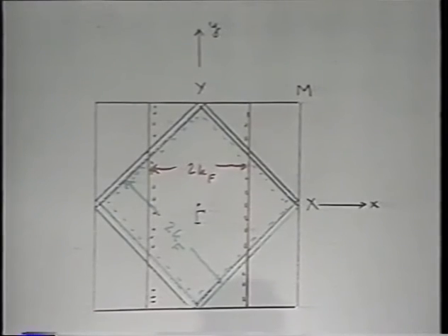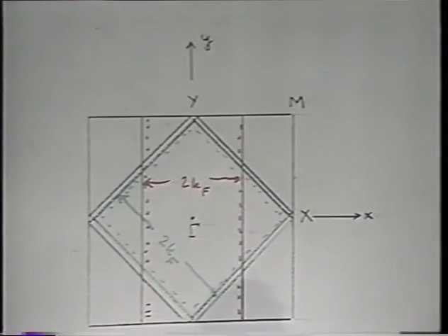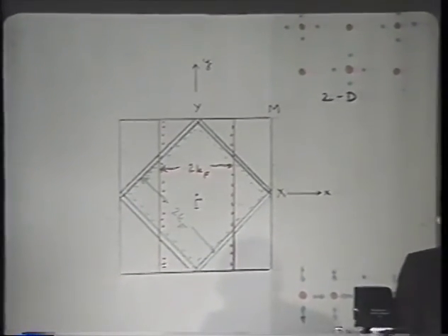They, too, give rise to sheet-like Fermi surfaces, these chains, I mean, but they have a different k Fermi and a different spanning vector. So we have truly a superposition of two types of Fermi surfaces, and this can affect k-space in a much broader fashion than otherwise.